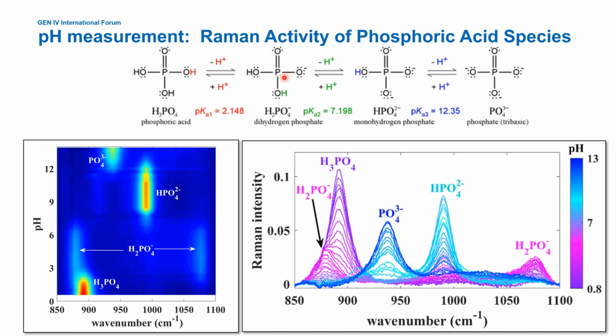And so as a function of pH, you have a lot of speciation of phosphate. Turns out each one of these species is Raman active and has a characteristic Raman band. This shows a spectrum of that speciation as a function of titration. This is the wave number across the x-axis versus the intensity. And we can see that the fully protonated form of phosphoric acid has a band here.